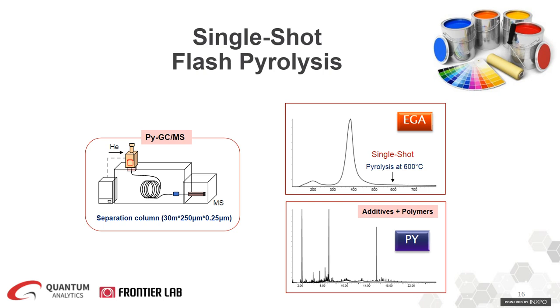And the key is that prior to that, we've run an EGA experiment in which we've been able to find the correct temperatures for the first and second shot, such that we are just removing the volatiles, the thermally extractable small molecules in the first step, and retaining the polymer information for the second step, flash pyrolysis. So in that case, the pyrolysates of the second step of a double shot will be the same as the single shot. It's just that there won't be any additives or small molecules in the way. So the libraries can be used in either of those flash pyrolysis modes for identification and characterization.